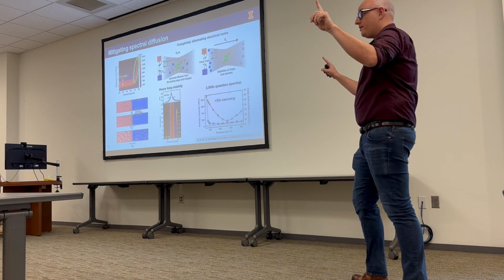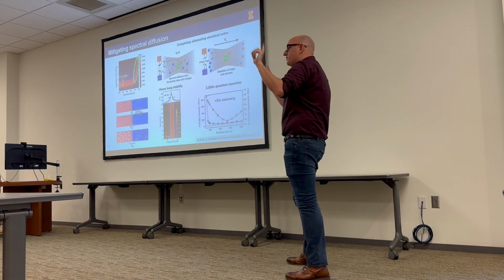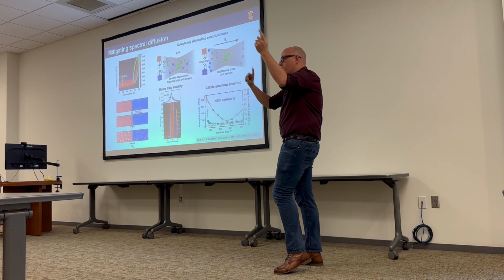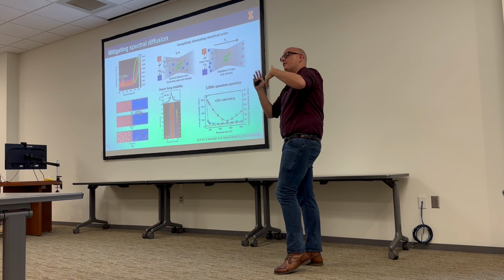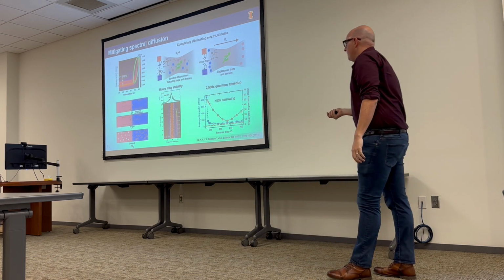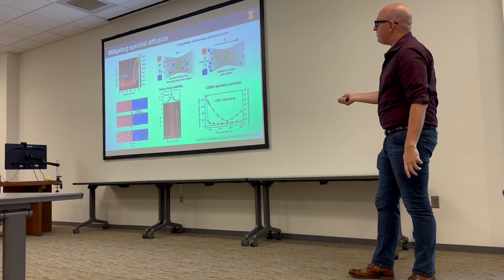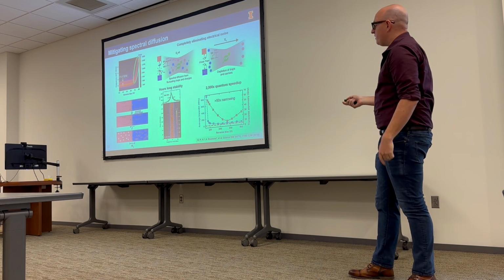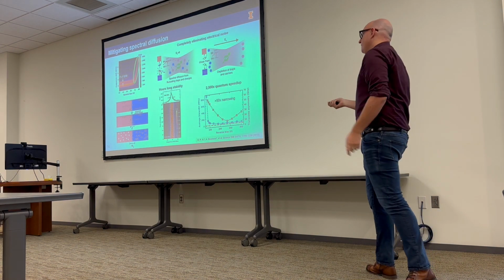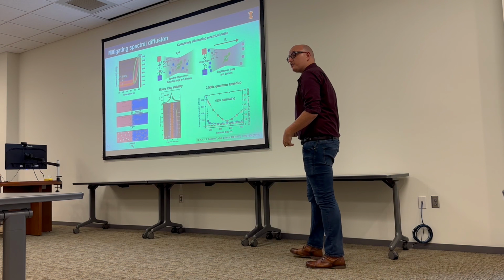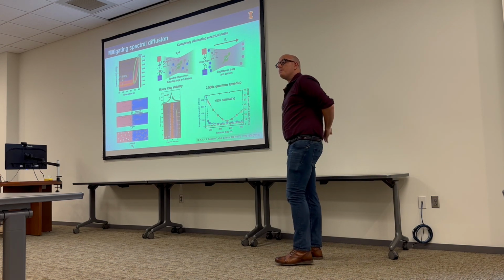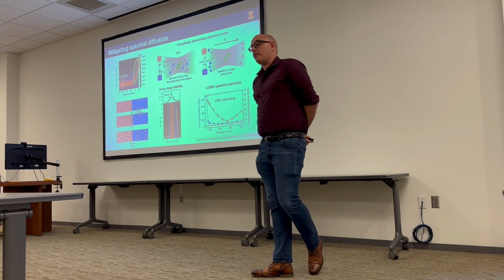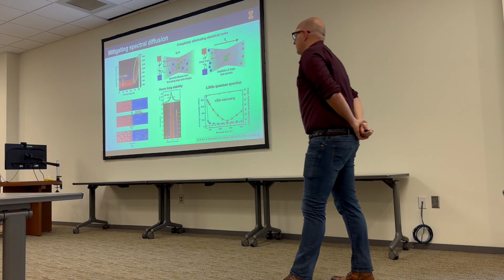And so if I told you that these photons need to be indistinguishable when they hit the beam splitter, if both of them are jittering around in frequency, that interference doesn't happen with high fidelity. And it turns out that basically a factor of 50 in narrowing, which is what we showed for two photons interfering, is maybe something like a factor of 50 squared in the speed up of the interference. What temperature is that using? This is all 5K.